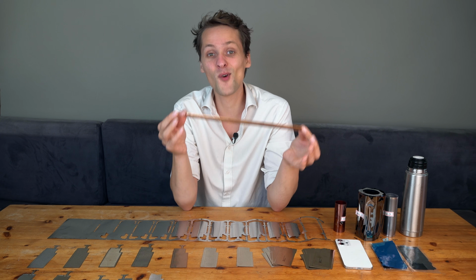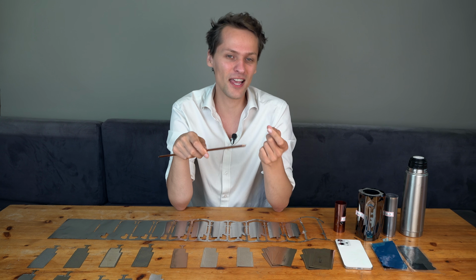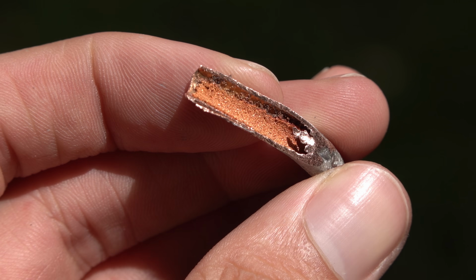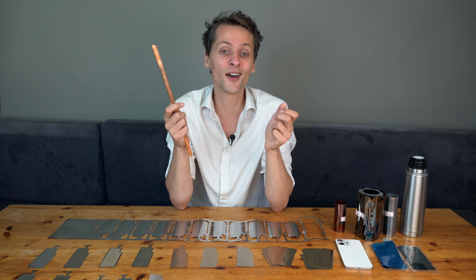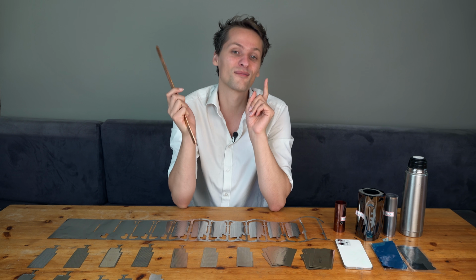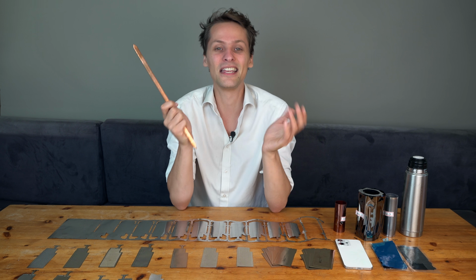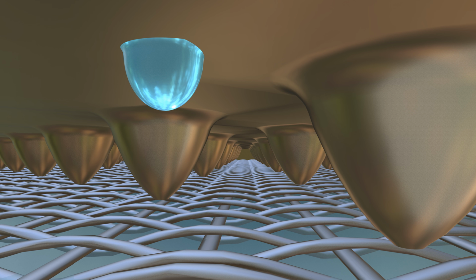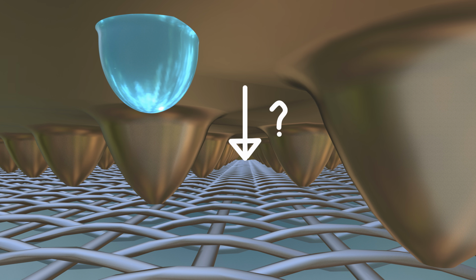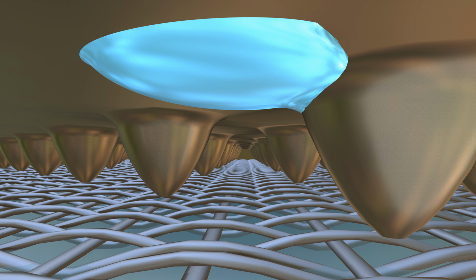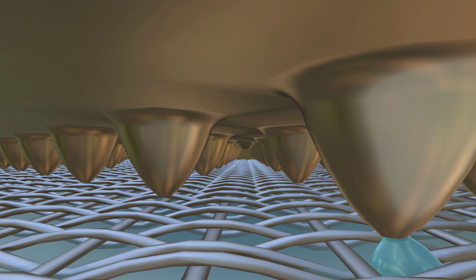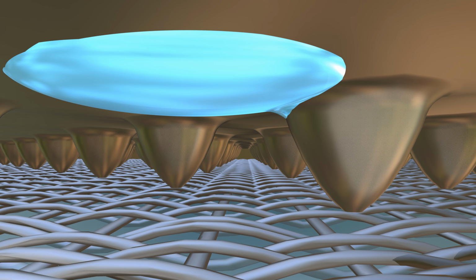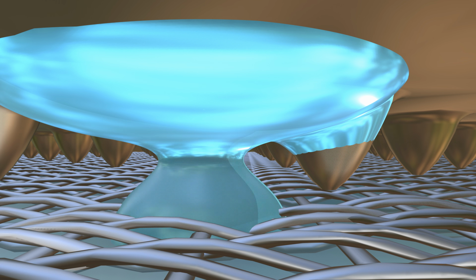Heat pipes have the same working principle as vapor chambers, but they generally have a sintered powder on the inside as the wick. And you can imagine that you might be able to do something like that, but then very thin, as an oxidation step, for example. But one of my favorite improvements that they're working on is as follows. The water on the top layer needs to go down again. Currently they have a hydrophilic coating to decrease the water angle so that these pillars transport it down. But in between the pillars, droplets can get larger and sometimes reach for the wick on their own. Why not treat it to make the water angle higher so it touches the wick earlier?